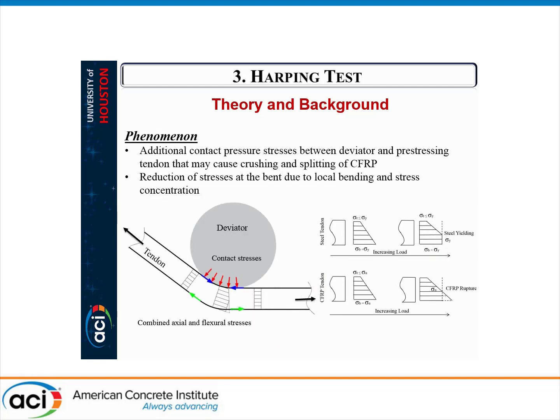This slide shows the distribution of stresses in a harped CFRP at the location of the deviator. First of all, we have the contact pressure, which is indicated with a red color in this figure. This contact pressure will increase by reducing the deviator size and increasing the harping angle or reducing the contact surface, which can lead to premature failure of the CFRP due to weakness of this material in the transverse direction. However, in the case of steel, we don't have this concern. Also, due to bending of the CFRP at the deviator location, we have the induced tensile flexural stresses indicated with green color, which can reduce the overall capacity of the tendon. However, again, for steel, due to ductility and yielding, this won't have any effect.